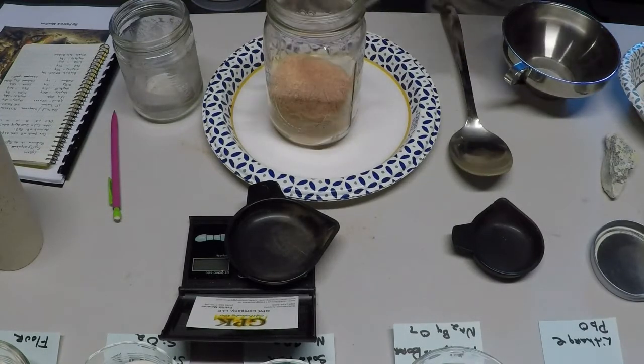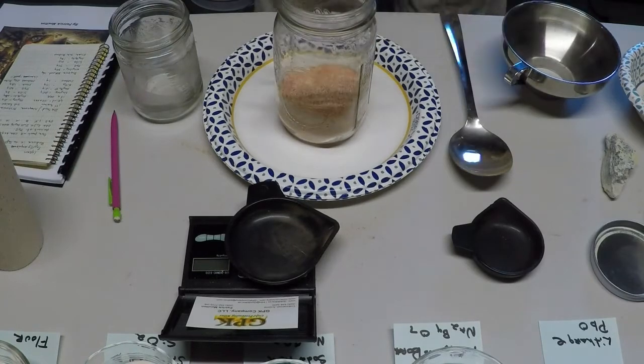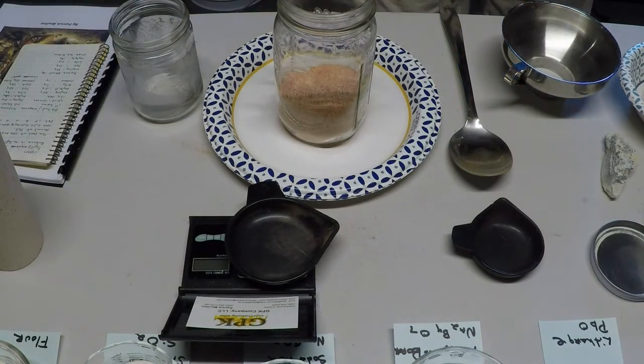Let's start with this material right here, this orange material right here. This is the high litharge flux. It contains a high amount of lead oxide in it, and smaller amounts of the other components. What I do is I just take this high litharge flux and then I add whatever components I want to match my flux recipe. This litharge flux here runs 70% lead oxide, 23% sodium carbonate, 4.5% anhydrous borax, which is super low, and SiO2, which is silica sand, at 2%. So it's really starved on the bottom end of it, but it's real high on the litharge end of it. And so what that does is that allows me to adjust the flux to whatever mixture and recipe that I need.